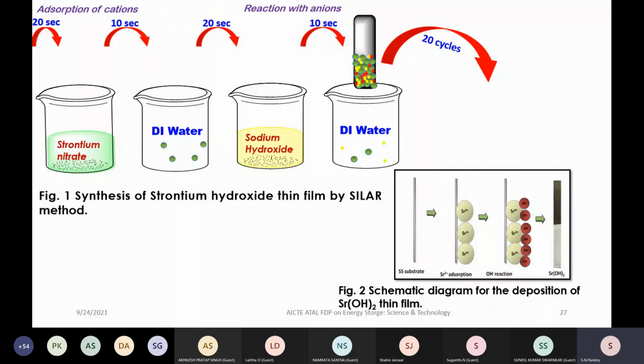So one can see here the schematic diagram of the deposition of this thin film. The substrate is here. So the strontium ion is being adsorbed, then it is reacting with this OH ion. So strontium hydroxide has been formed. So manually we have done it, and after the sample has been prepared, then we have to characterize it, to see whether whatsoever sample we tried to make has been formed or not.